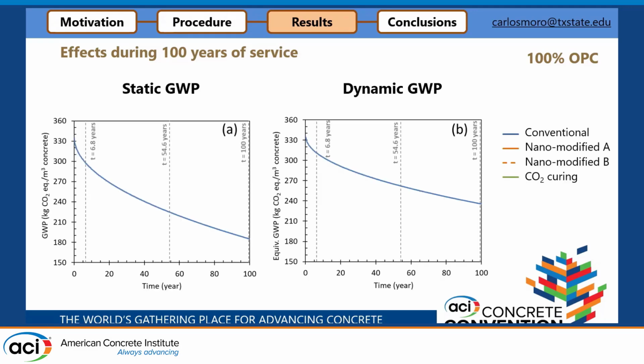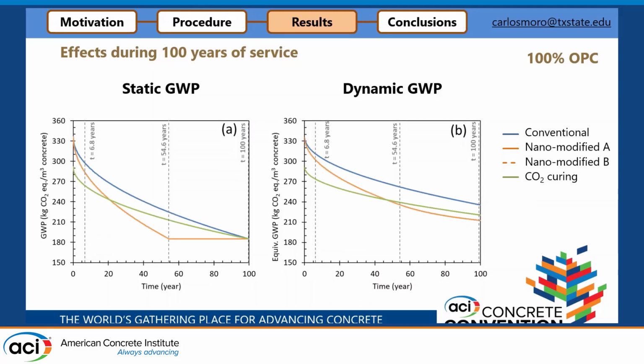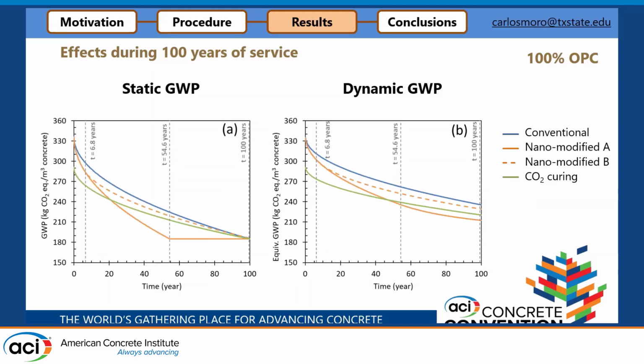Okay, so this happened in the first thing, but how does this affect the global warming potential in the whole life, in the 100 years? So we do exactly the same thing. I plot here the static values and also the dynamic values with the 4 different ones: the conventional one, the CO2 curing, the nano-modified A, and the nano-modified B. As you can see, all these values are ending in the same point using the static, but none of these concretes are ending on the same point using the dynamic.